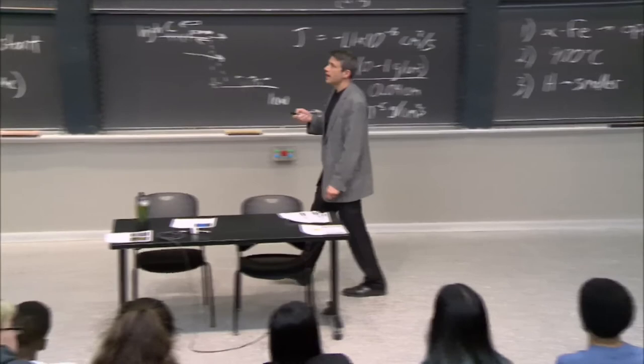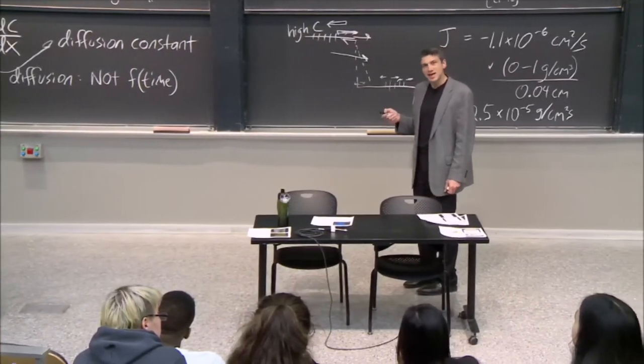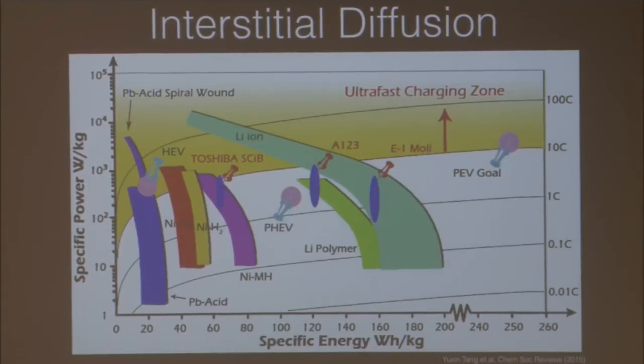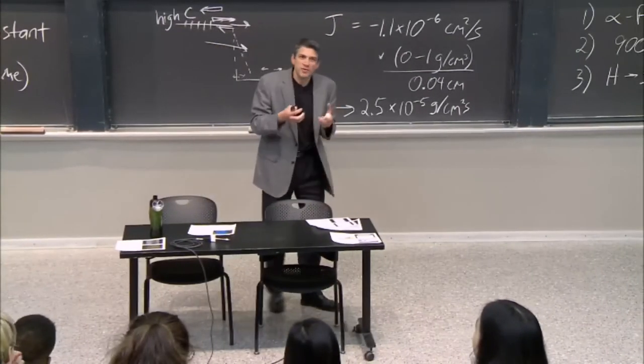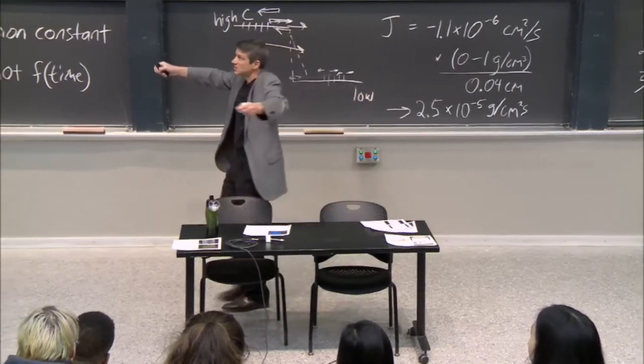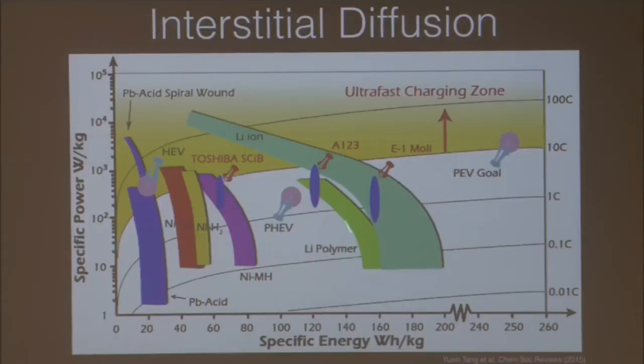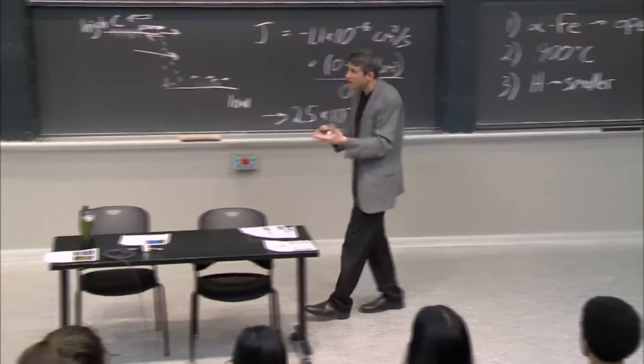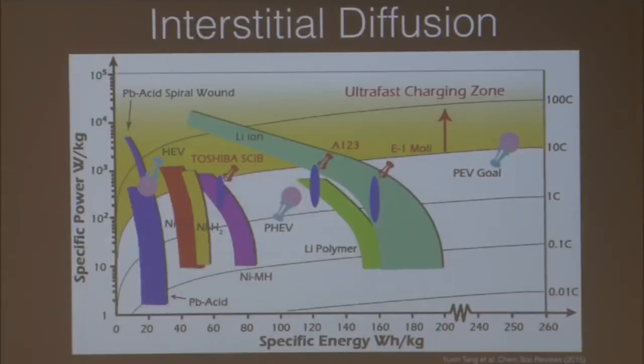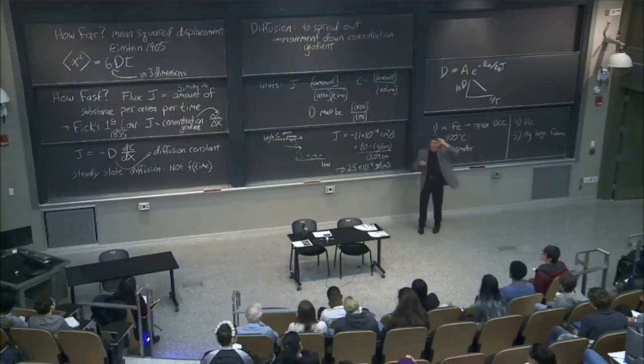Polymers could be slower — it makes sense. When we talk about polymers, it's harder to make crystalline polymers, to keep a polymer from having some amorphous region. After all, you've got these 100,000-unit-long strands of spaghetti. So diffusion is going to be lower in a polymer than in one of these crystals, like an olivine lithium iron phosphate. But polymers would be great because they're lighter and flexible, and we want them for many applications. These are the kinds of trade-offs you think about, and diffusion D is right there in the center — because none of us want a battery that takes two days to charge.